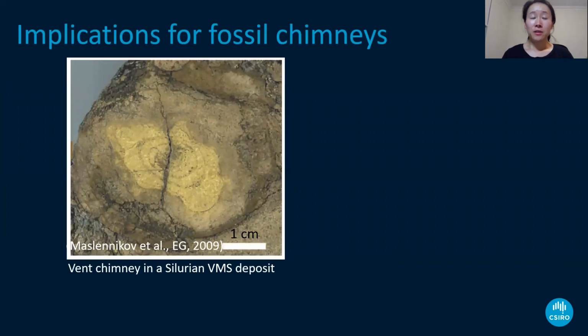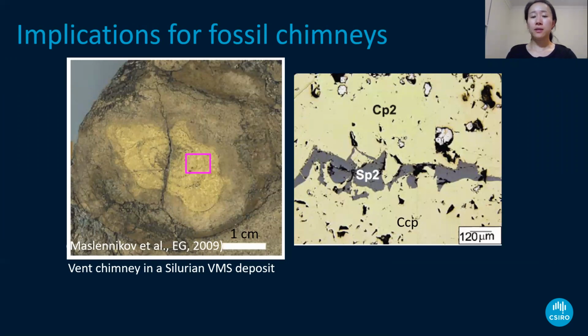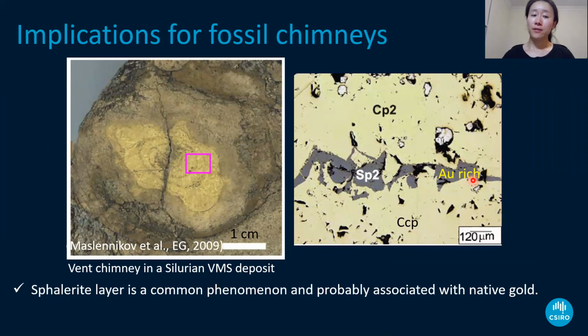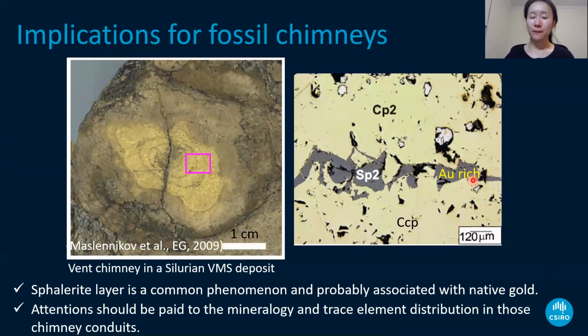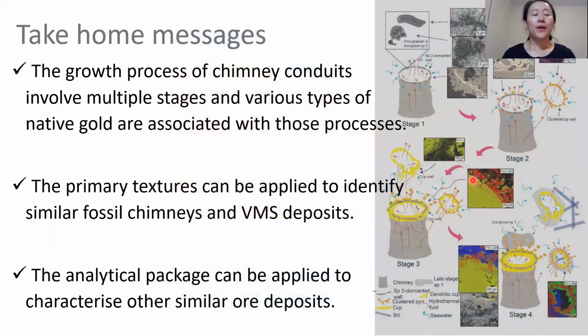We also find a similar observation, but maybe not exactly, in the fossil chimneys from a Silurian VMS deposit. In this chimney, very close to the center, the authors reported that a thin sphalerite layer segregated the different generations of chalcopyrite, and the sphalerite is gold-rich as well. So here we propose that the thin sphalerite layer represents the early stage of the fluid mixing. It's very common in fossil and modern chimneys, and they are gold rich. So if one wants to target native gold in such samples, then this could be the potential area you should target.